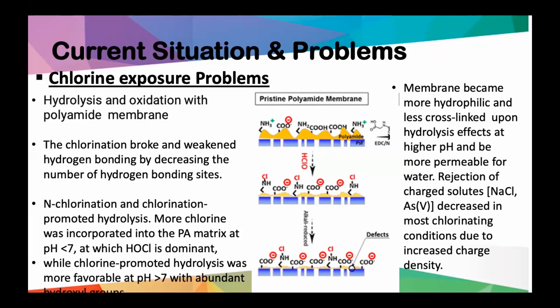But still, we have some traces which go through to the polyamide membranes. We want to say here that if only 1 ppm, meaning 1 milligram per liter, of chlorine goes through to the polyamide layer of the RO membrane, it causes some destruction of this layer. Chlorination plays an important role with the amine group, which is the main functional group used in the polyamide and plays the main role in separating the monovalent ions and salts from the feed water, from the seawater or brackish water, giving permeate water free of salts.